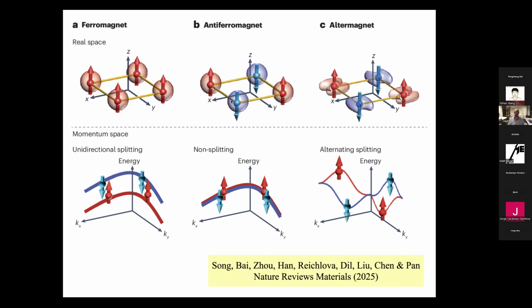An altermagnet is different, and it shares some characteristics of an antiferromagnet and some of a ferromagnet. It shares the characteristic of an antiferromagnet in that there is no magnetization. The total net magnetization is 0 by symmetry. However, there are higher order distributions, or a spatial distribution of spins, that is such that there is a splitting of the bands in momentum space. And this splitting of bands in momentum space is determined by the symmetry. In that sense, an altermagnet looks more like a ferromagnet.